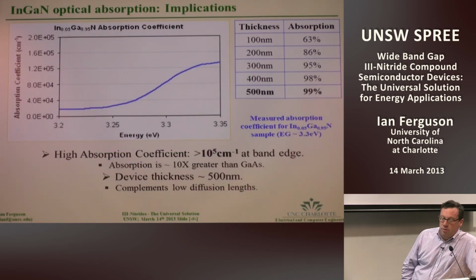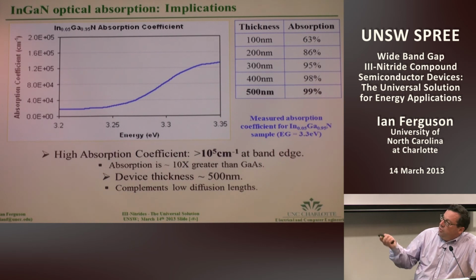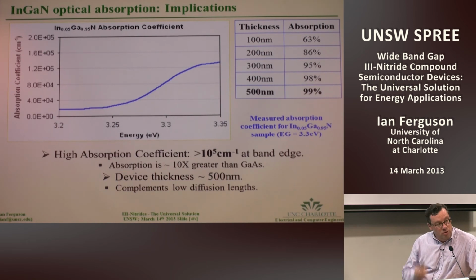As I mentioned, the other issue we had originally was with absorption coefficients. So when we were originally designing, we were designing thicker materials, but what was good is we discovered the absorption coefficients were much larger than we were expecting. So we could actually end up designing devices around this 200 to 300 nanometer thick region, which was getting close to the depletion region of the material.